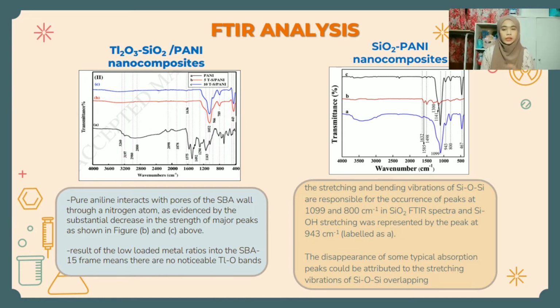For silicon dioxide polyaniline nanocomposite, the stretching and bending vibration of the silicon bond are responsible for the occurrence of peaks at 1099 and 800 per centimeter. In silicon dioxide FTIR spectra, Si-OH stretching was represented by the peak at 943 per centimeter. The disappearance of some typical absorption peaks could be attributed to the stretching vibration of the silicon bond overlapping.